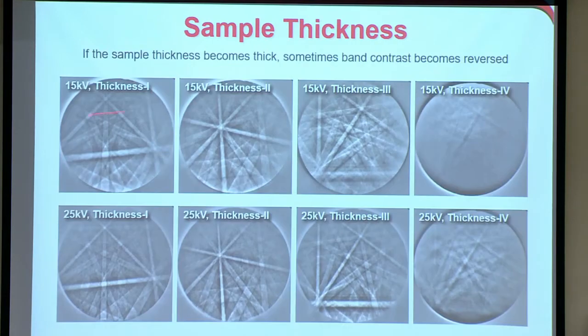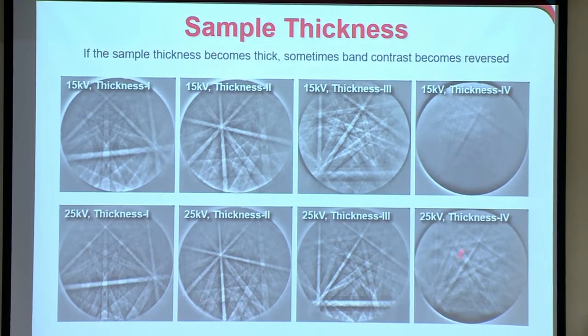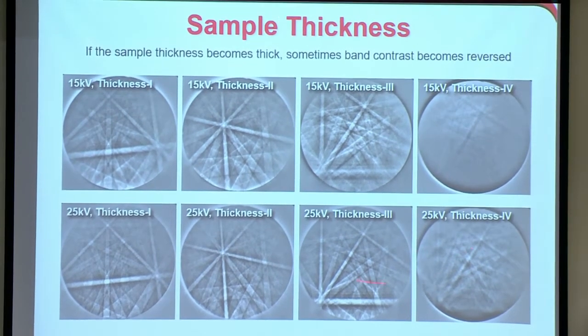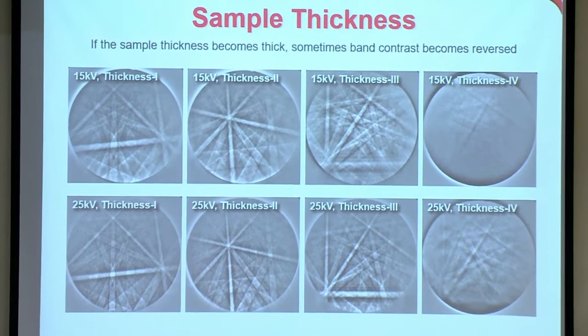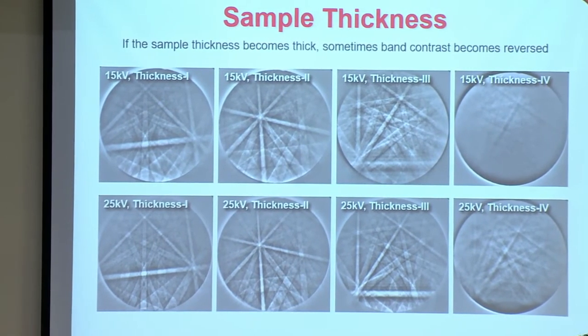But we can do EBSD then in a transmission mode, essentially, or we can use our EBSD detector on a transmission sample. Now, if the sample becomes really thick, you'll see we get a reversal. Instead of the bands being bright, they're actually dark, so we get an intensity reversal. And sometimes in a single pattern, you kind of see it here, you can get both bright and dark, which really causes trouble when you're trying to index them.